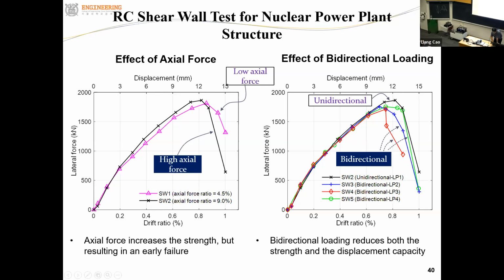And the figure on the right-hand side shows the comparison between the unidirectional loading and the bidirectional loading. The unidirectional case here, the black line, is the same as this one. And these are the results from the bidirectional loading with different loading patterns. We can see that for strength and initial stiffness, we do not have any significant difference between the unidirectional and the bidirectional one. However, there is a strength reduction as well as early failure of the system if the bidirectional loading is applied to the wall system.